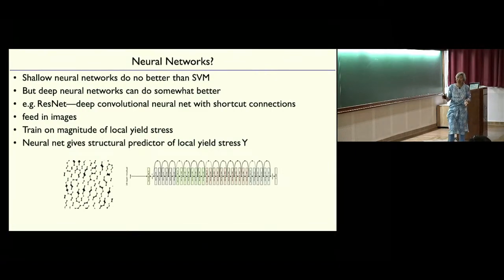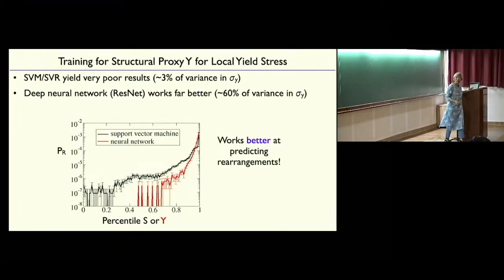We actually use the same kind of network that's used to distinguish cats from dogs, but we give it a little neighborhood around our central particle and train it on these images to get a structural predictor of yield stress, which works quite well. In fact, it works better than softness at predicting rearrangements. It's not trained on rearrangements, it's trained on local yield stress. But if I look at the probability of rearranging versus the percentile of S, or this structural predictor of yield stress, Y, what you see is that the probability of rearranging is a steeper function for Y than it is for softness, over a smaller range. So it's actually a better predictor of rearrangements. And I'm sure one could do even better.